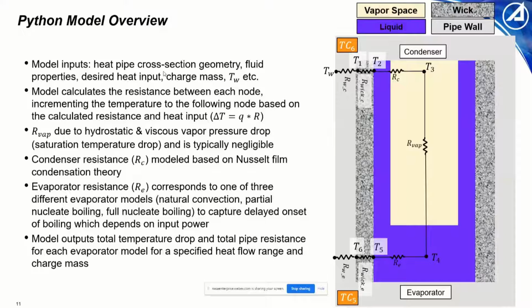Because of that, we needed to enforce some temperature constraint along this node network. It could be any value, but we opted to use the condenser outer wall temperature, which we've denoted to be TW, because typically this is a function of your heat rejection, and it's a pretty well-known temperature. A quick note is that these node numberings do not correspond particularly to the thermocouple values.